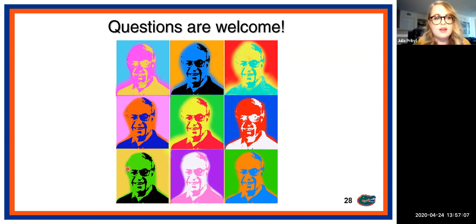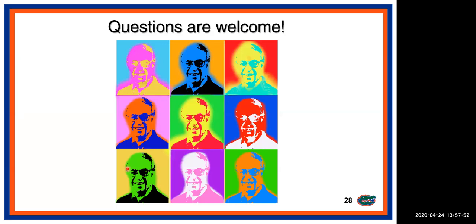Yeah, so there is actually a really nice paper, I can't remember the journal now, but it's from 2009, where if you precisely incorporate a hexyl branch, for example, so it's sort of something that looks like a linear low density polyethylene, but in a precise fashion, that work showed that the precision spacing of what would be a butyl branch lowered the distribution of lamellar thickness, and that was positively correlated to the tensile properties of that material. So it's kind of a nuanced change in physical properties, but that's definitely something that was observed as a result of the precision. Okay, thank you very much.